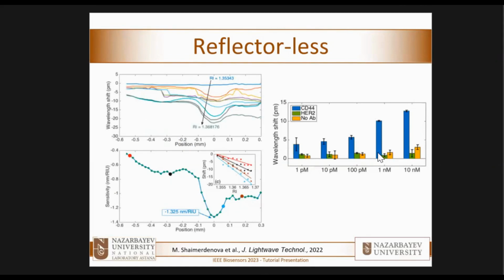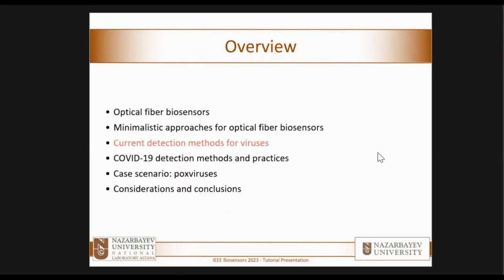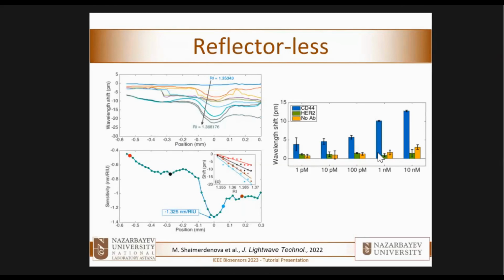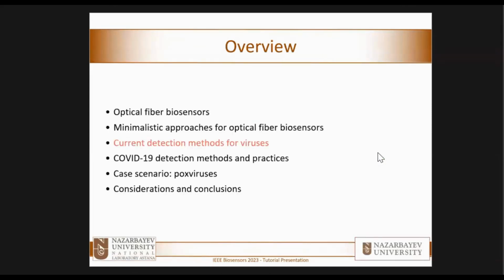This is how you detect using distributed sensing. Notice this is distributed, so we get a wavelength shift at every single point of the fiber. This chart has 10 micron resolution. When you approach the center of the taper, the waist, you get more sensitivity. When you mark that point, you can see how the wavelength shifts, and you can get a quite accurate detection. This method is still developing, but I think it's a good one because it's also quite fast to make. So that's about optical fiber biosensors, minimalistic approaches.